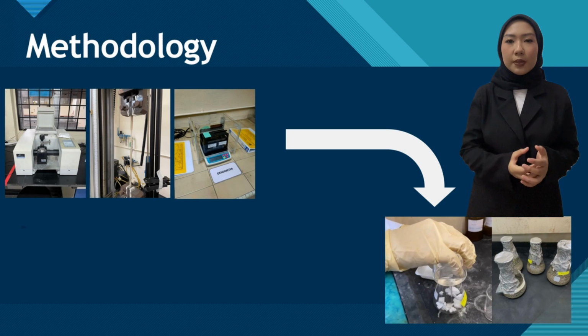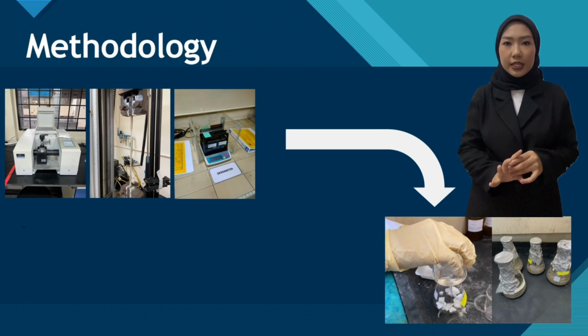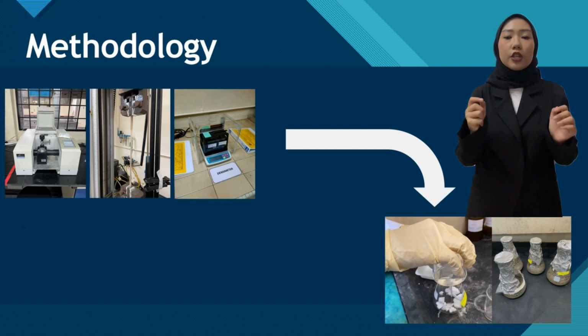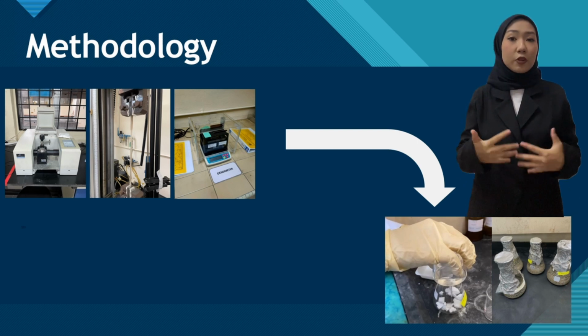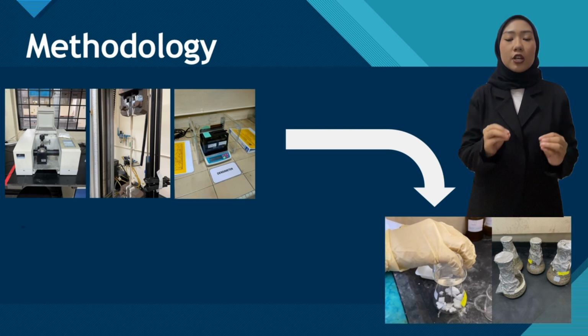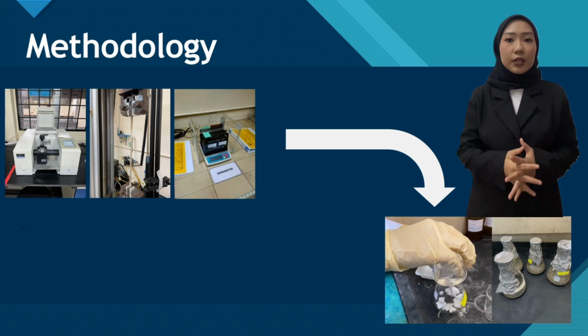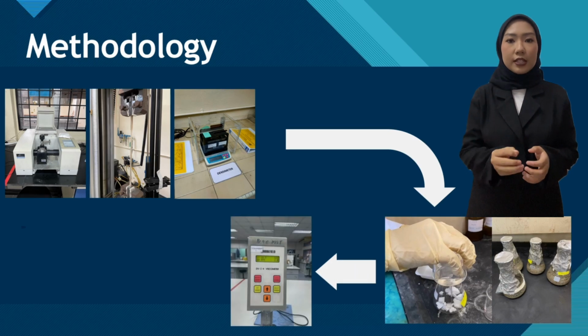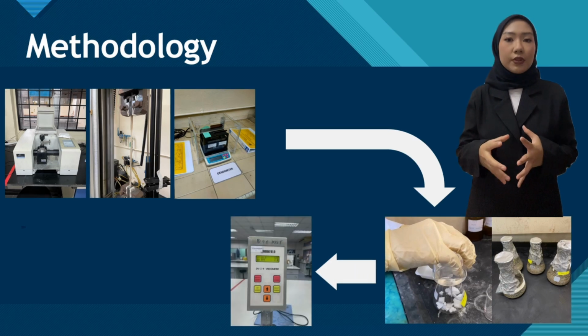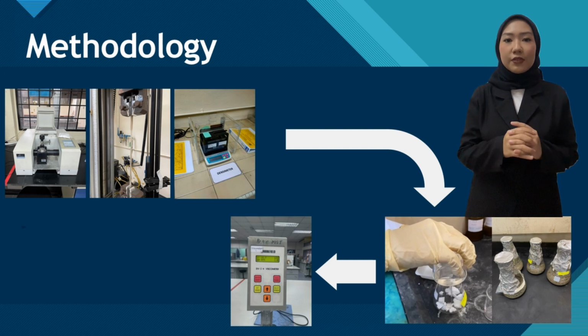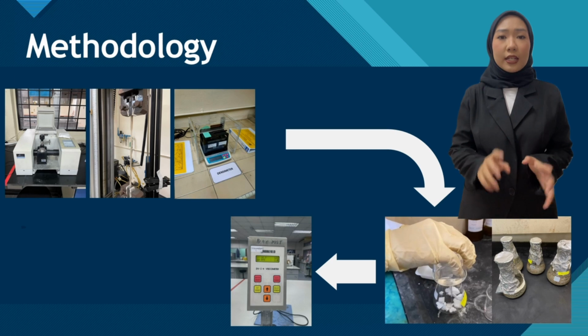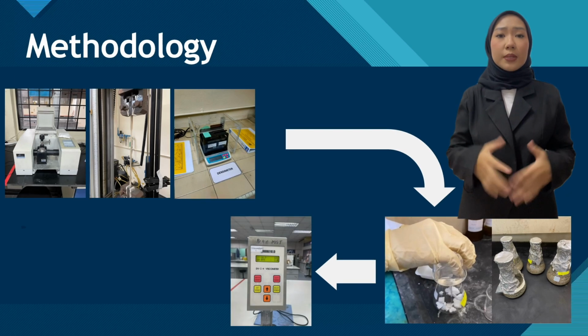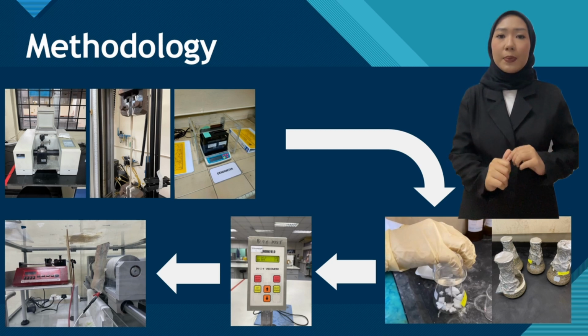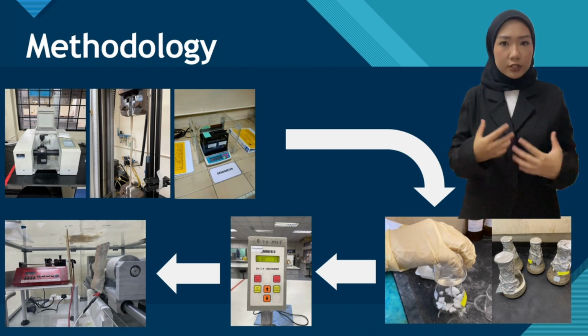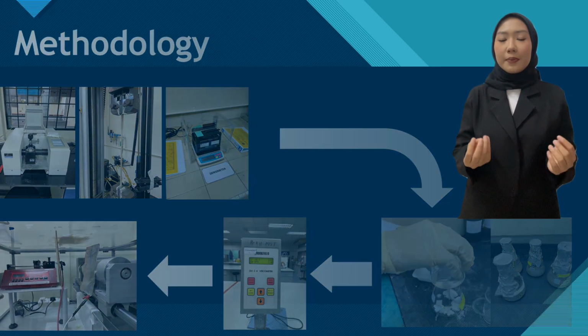The process of making a solution by dissolving different concentrations of recycled LDPE in xylene and toluene solvent failed due to the absence of heat, because the process was time-consuming. The material was replaced with different concentrations of expanded polystyrene mixed in xylene solvent, and it was successfully dissolved. Then, the viscosity of the solutions of different concentrations of EPS and xylene was tested using a viscometer. This test cannot be done for the recycled LDPE solution due to the unsuccessful solution making. Then the solutions of different concentrations of EPS and xylene were used for electrospinning. Then the product from electrospinning was observed under a microscope.